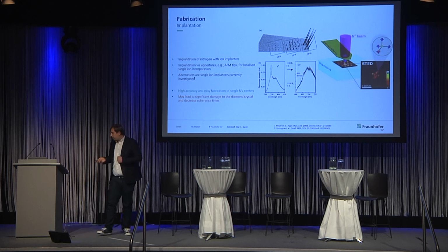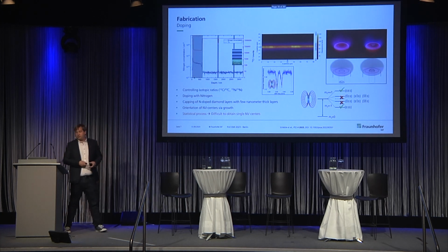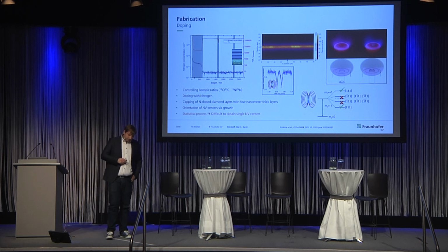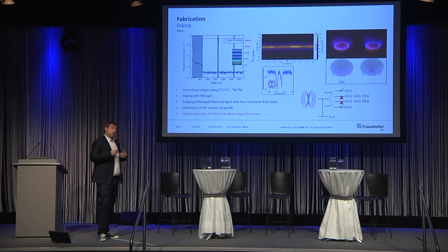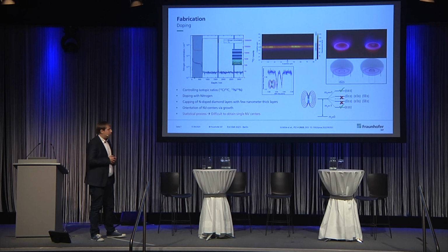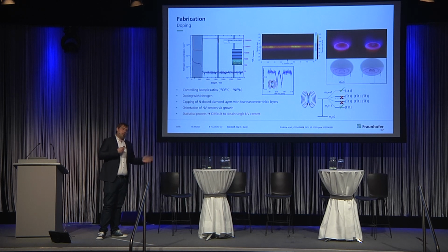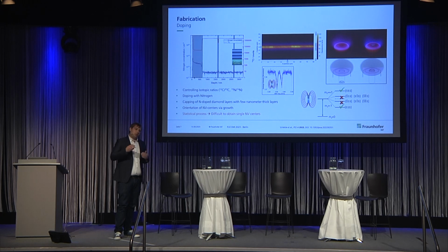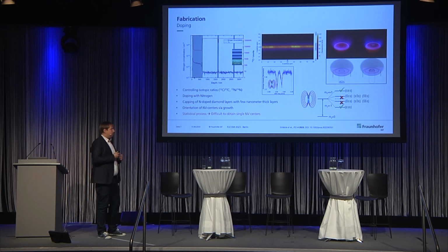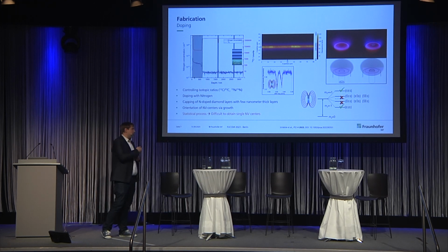Another approach that we are actually following is integration via growth. What we can do is grow nitrogen into the diamond during a CVD process, so the diamond is grown by chemical vapor deposition. With that, we don't only control the integration of nitrogen, but also the surrounding of the nitrogen, meaning that we can use isotopically pure gases, which lead to less decoherence due to nearby nuclear spins. Or we can position nearby nuclear spins for some reasons that I will show later.